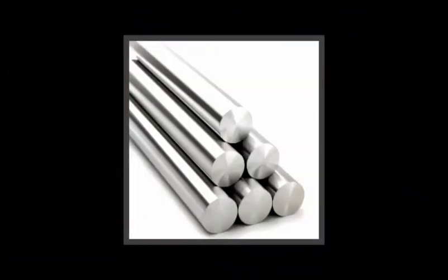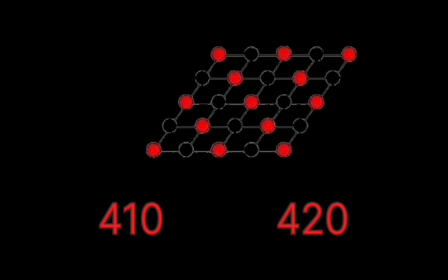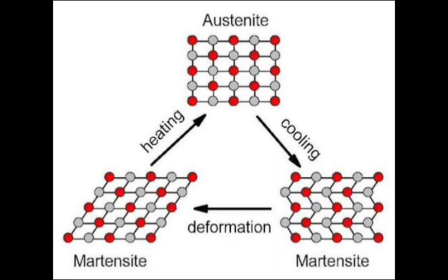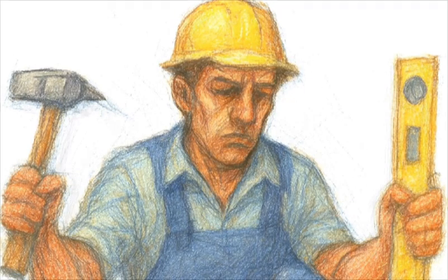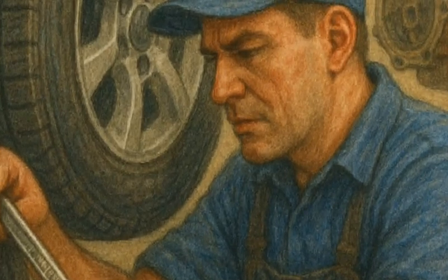Stainless steel, an iron-based metal that is, by definition, at least 10.5% chromium. There are these subgroups. 410 and 420 are martensitic and can be hardened, for instance, the blade of a chef's knife. Or the tradesman's tool. These are fairly low in chromium. They trade off their corrosion resistance for the ability to harden.